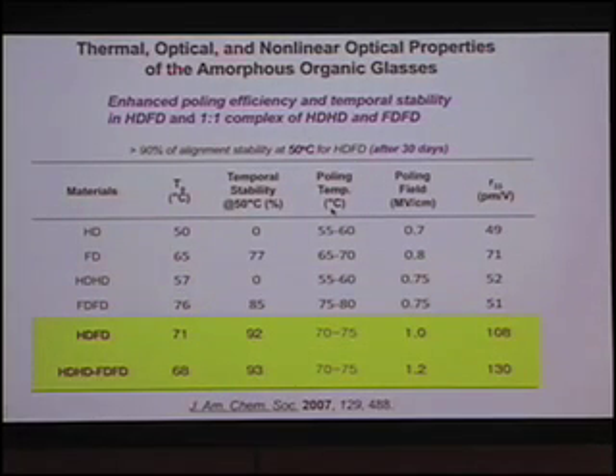And this is the result, to briefly show you. When we have just a single dendron, you don't really see a significant enhancement of your electro-optic activity. But when you show this as a symmetrical HDFD type of arrangement, you immediately have an effect of a 2 to 2.5 times enhancement of your electro-optic activity. But most importantly, the material has a relatively low Tg. When you heat it up after you pole-align them, with long-term heating at 50 degrees C for 30 days, this material still retains about 92% of its original alignment. This means the interactive forces really kick in to maintain the lattice polar order.